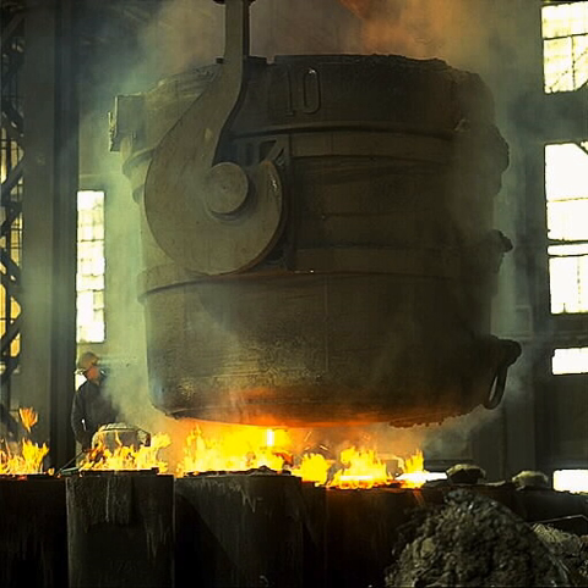Other alloying agents, manganese, chromium, molybdenum, titanium and vanadium, counteract silicon, promote the retention of carbon, and the formation of those carbides. Nickel and copper increase strength and machinability, but do not change the amount of graphite formed. The carbon in the form of graphite results in a softer iron, reduces shrinkage, lowers strength, and decreases density.